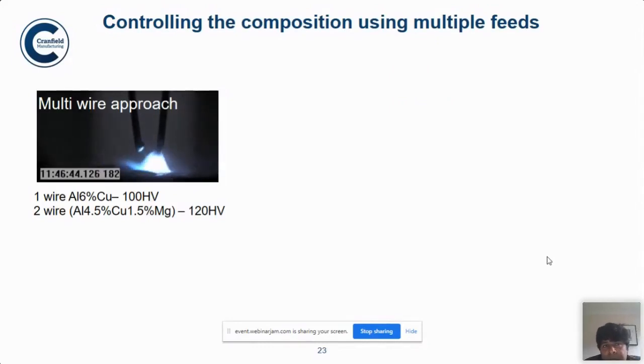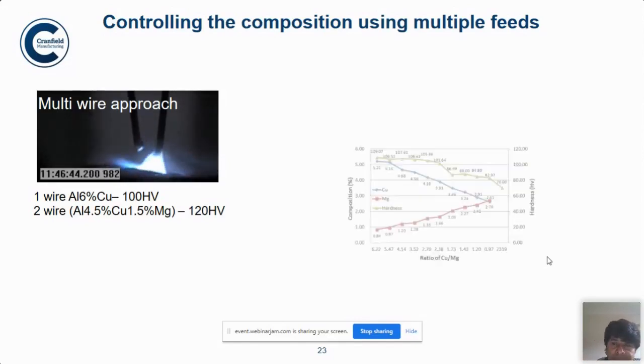Controlling the composition using multiple feeds. So this is one of the design flexibility or material design flexibility that is offered by the WAAM process. So you can have multi-wire in an arc. This is called tandem welding, or many people can say different names, but you can have different grades of wire going into the same pool, and thus you can really control the weld pool composition, and thus you can control the solidification path that the weld pool will follow, and thereby reducing chances of cracking and stuff.